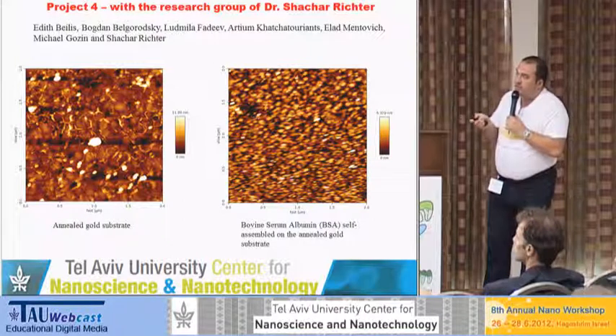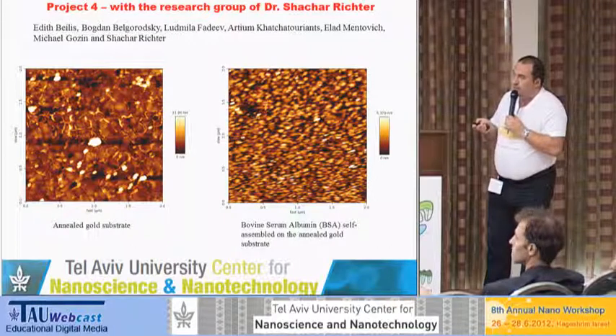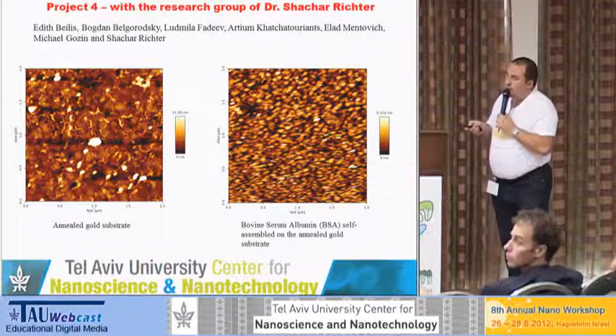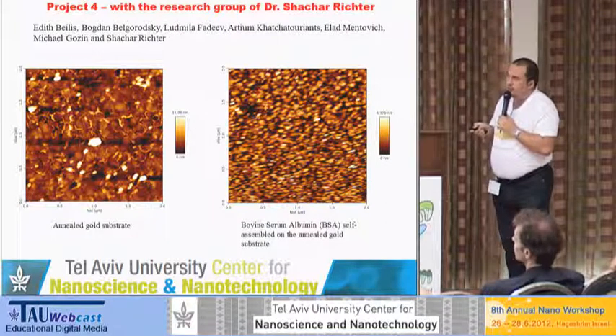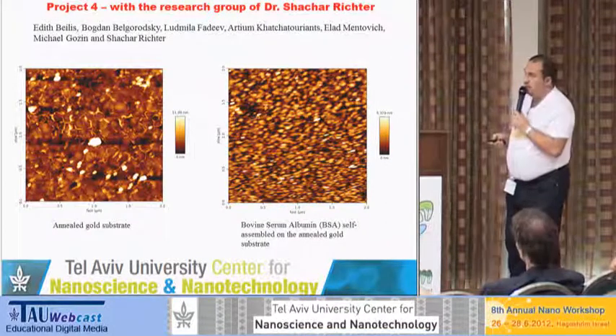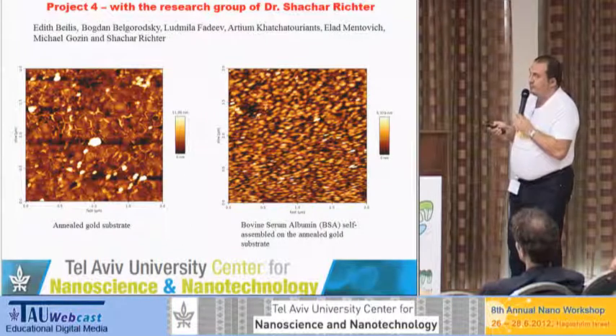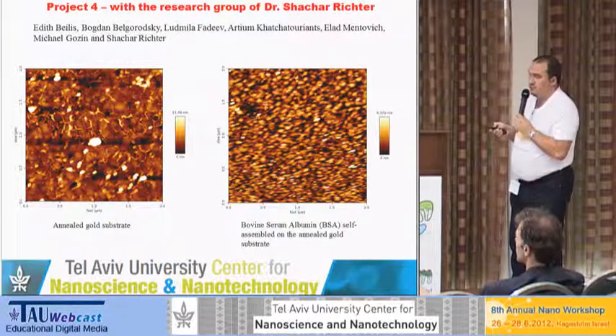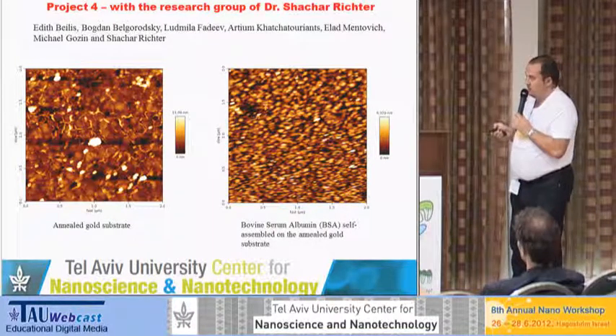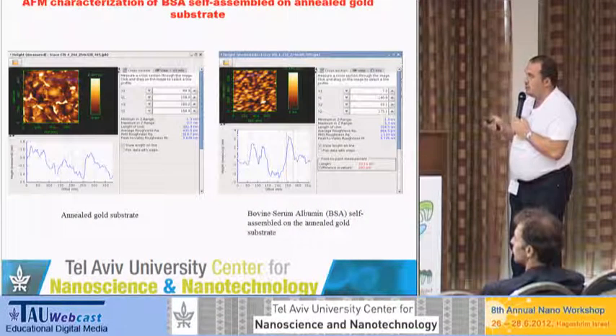Here, as you can see, the annealing didn't work that well, because you see some kind of walls and other residues on the sample. But still you can see that most of the sample is essentially flat. And after the adsorption of BSA protein, you can see this picture, and first of all you see that the pictures differ significantly, which is a good indication.